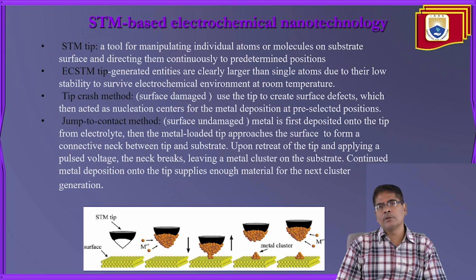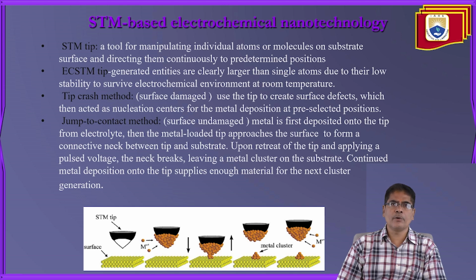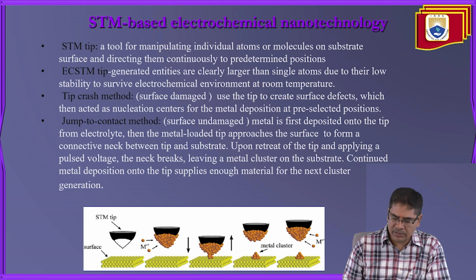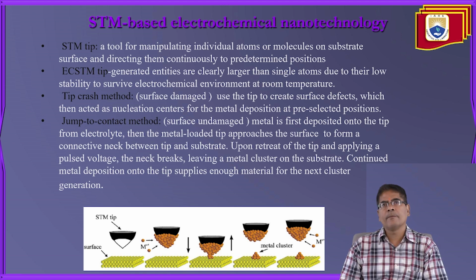The other method is the jump to contact method. Here the surface is undamaged; metal is first deposited on the tip from the electrolyte. The metal loaded tip approaches the surface to form a contact with a pulsed voltage. The neck breaks, leaving a metal cluster on the substrate. Continued metal deposition on the tip supplies enough material for the next cluster generation. So this is the STM tip, and this is the surface with a metal cluster. Okay, so these are some of the STM based electrochemical nanotechnologies.